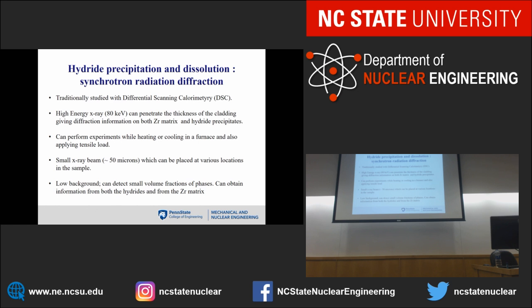80 keV. We can penetrate the thickness of the cladding. The cladding is about 0.6 millimeters. And I can give diffraction information on both the Zirc matrix and the hydride precipitates. So I can perform experiments also while heating or cooling in a furnace, and also while I'm applying tensile load. I have a small X-ray beam of about 50 microns, which means that I can be placed at various locations in the sample. And it has very low background, as I'm going to show you, which means that I can detect small volume fractions of phases.